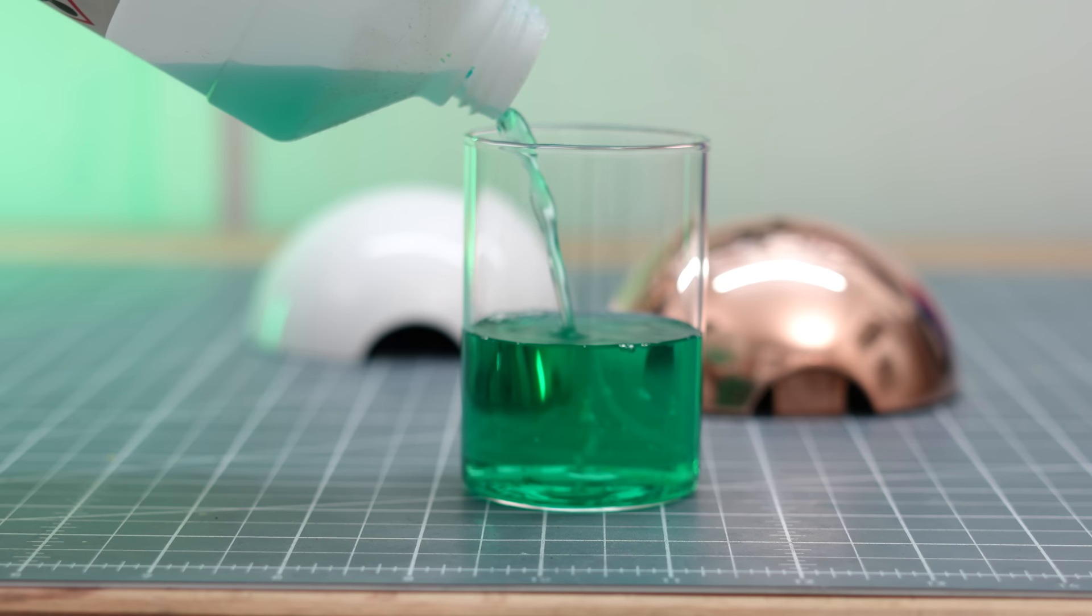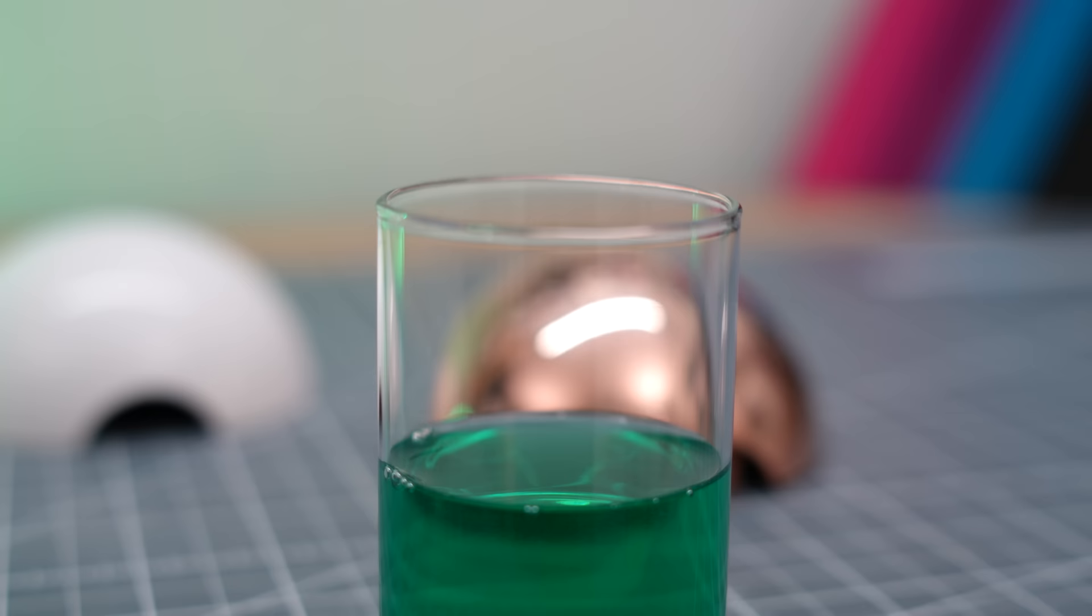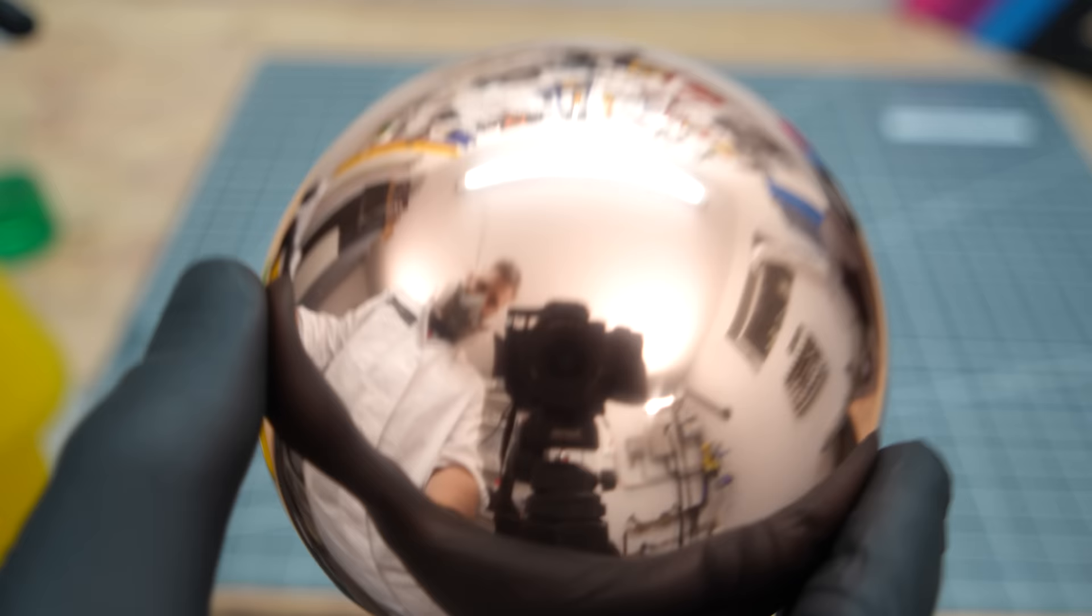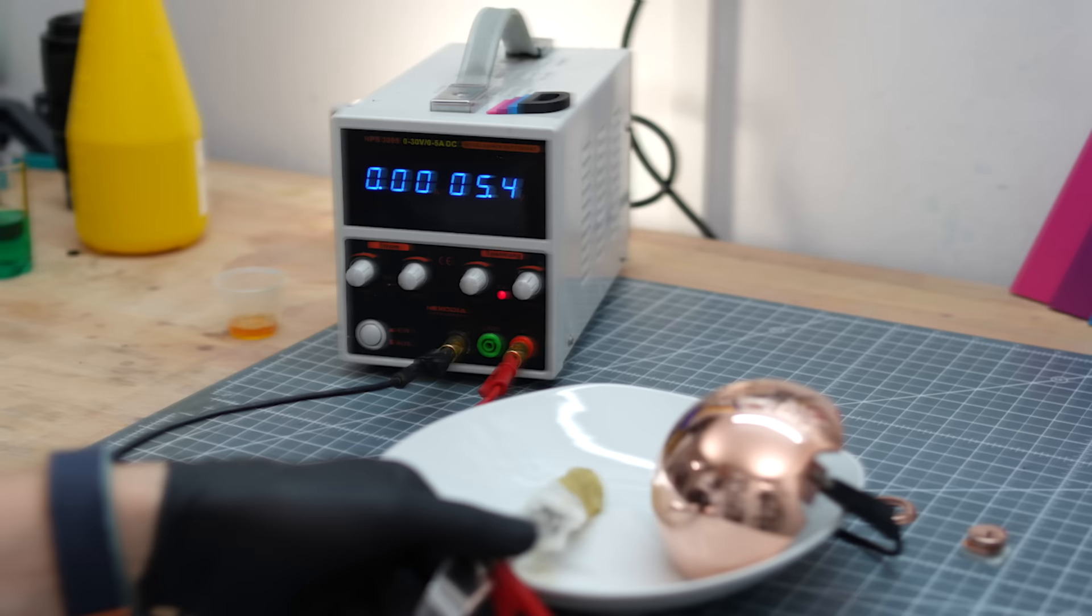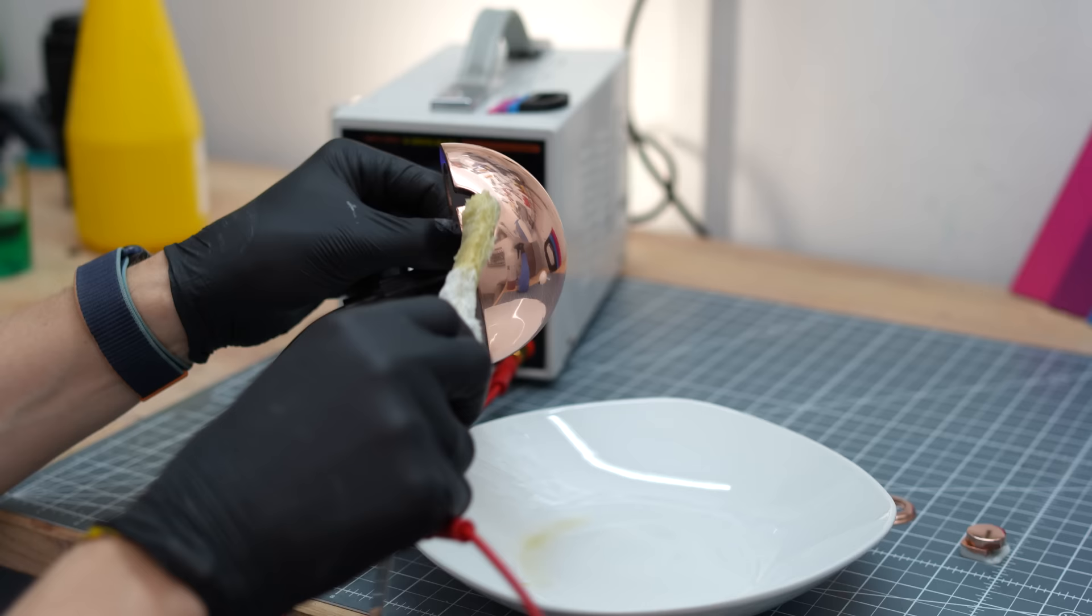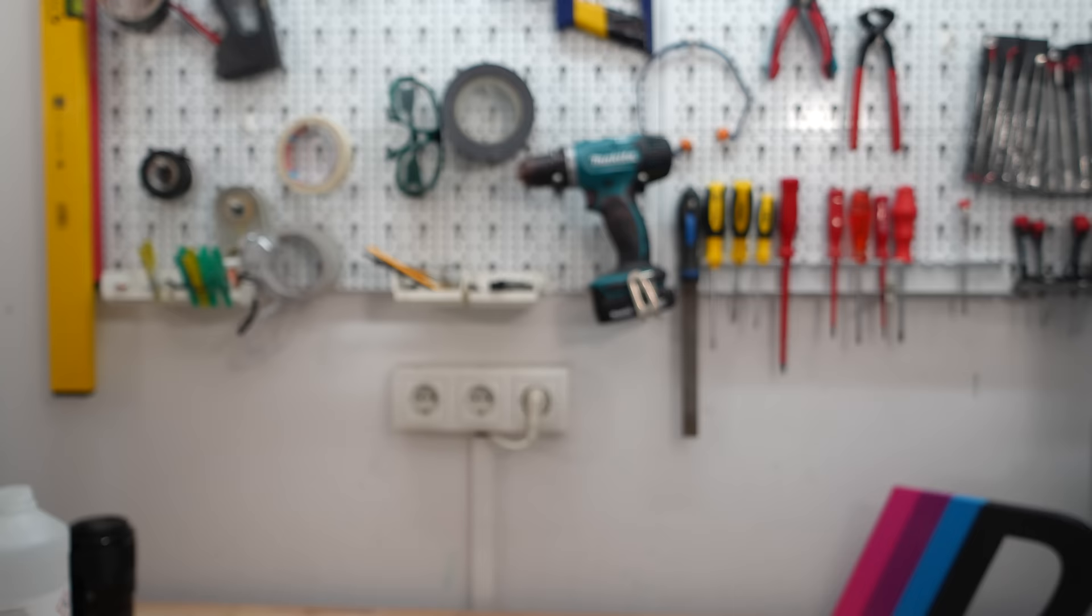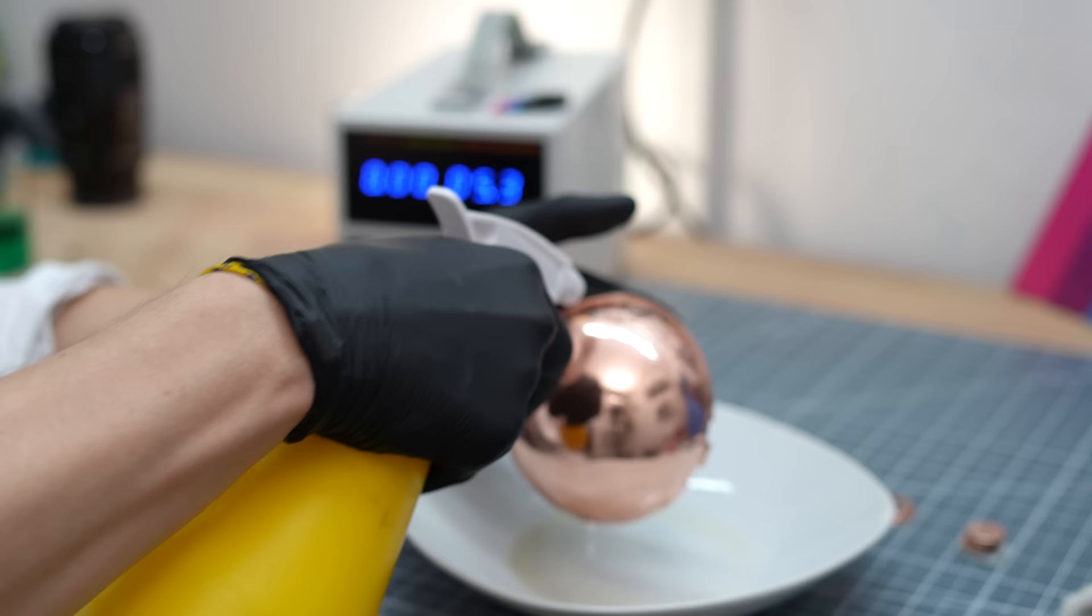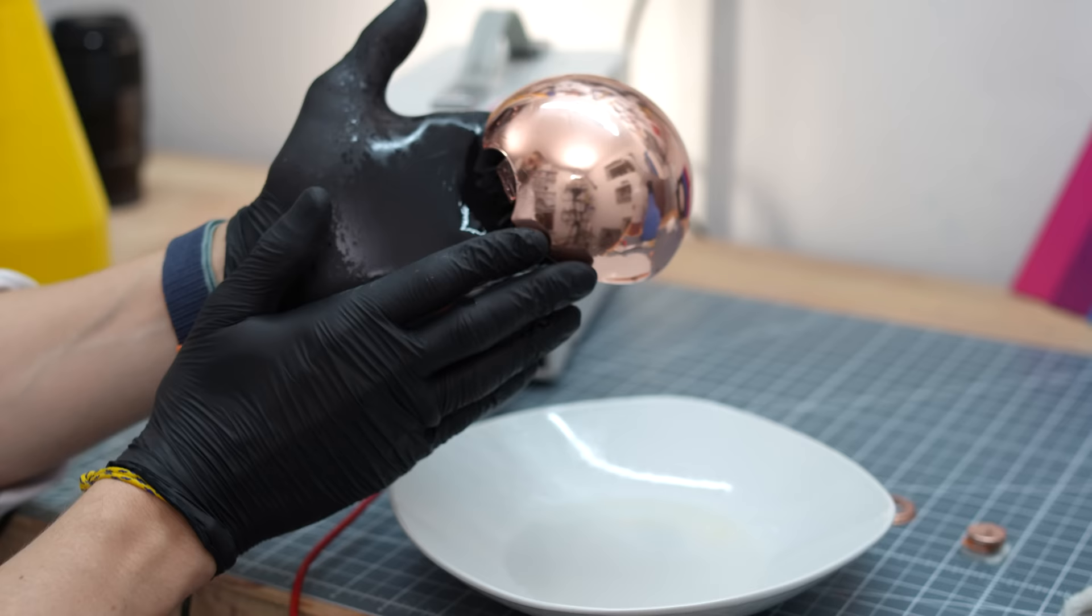Copper is nice and all, but now we need a layer on which we can electroplate gold later. Nickel and palladium are suitable for this purpose. Nickel is pretty toxic, you know, so wear a respirator and all that. I now electrically degreased the copper print with a galvanic degreaser and a voltage of about 6V. I use stainless steel as anode, which literally blasts off the grease. Then I activate the copper with a 10% citric acid solution. It all sounds complicated, but it's easy and unfortunately necessary.